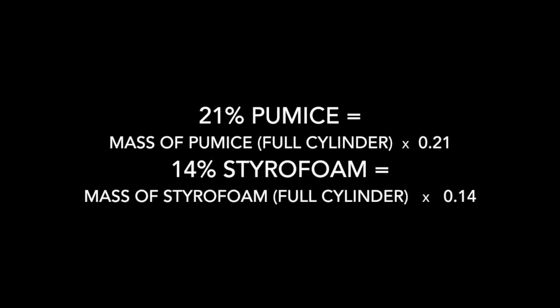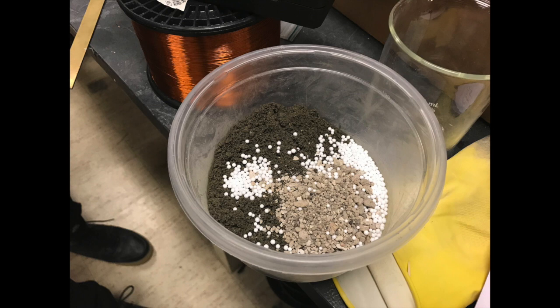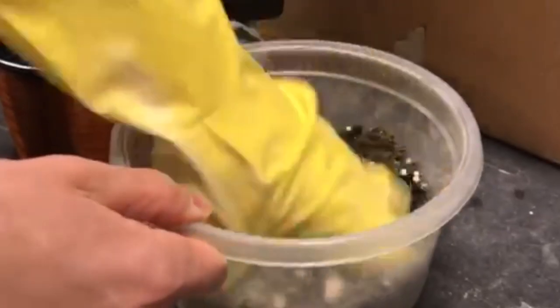Now you can move on to your own mixtures. Our samples consisted of 21% pumice and 14% styrofoam. We measured 21% of the total mass needed to fill one cylinder with pumice and did the same but with 14% for styrofoam. You will then mix these amounts with the same average mass of baseline concrete that you calculated previously. Mix them thoroughly in a bowl.